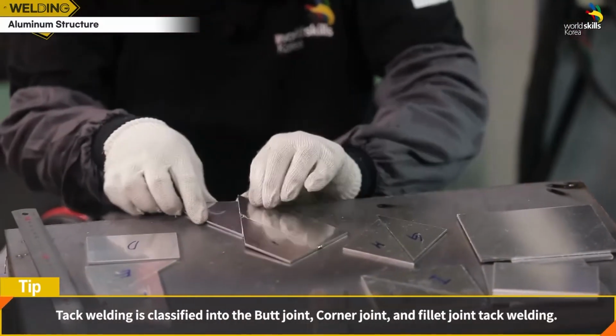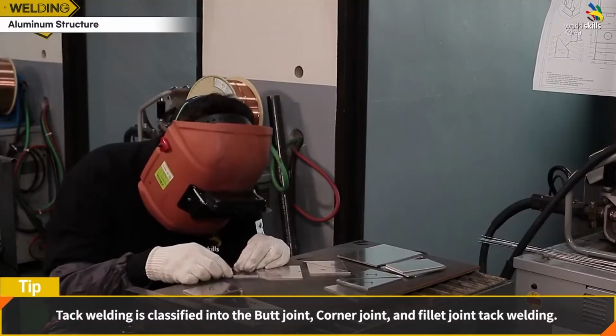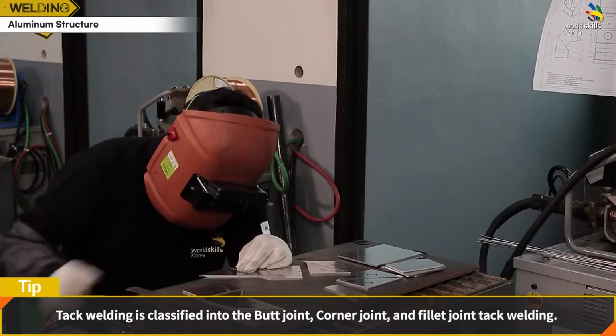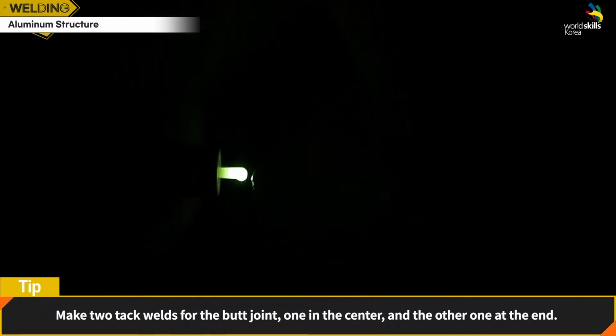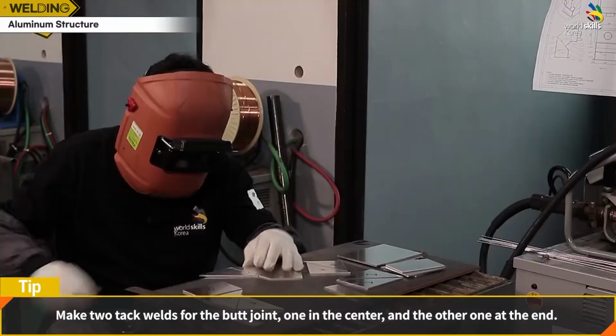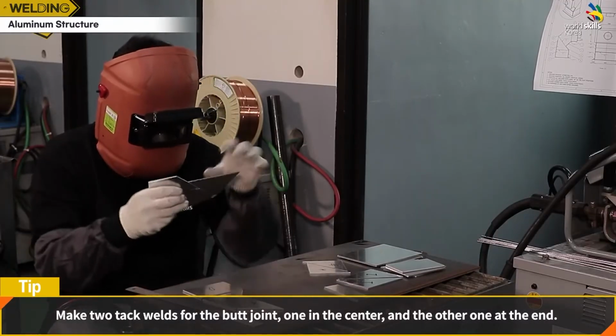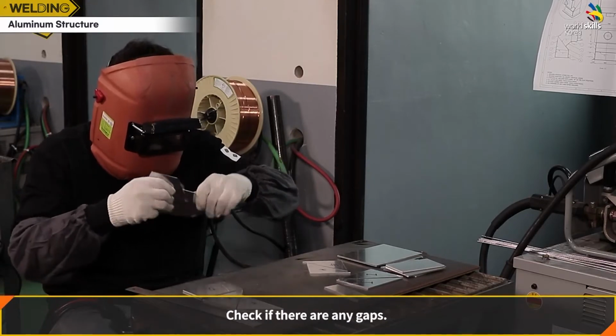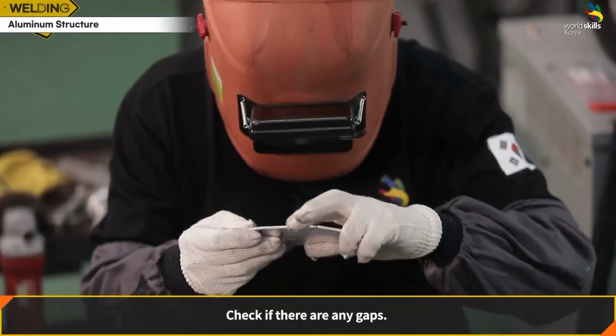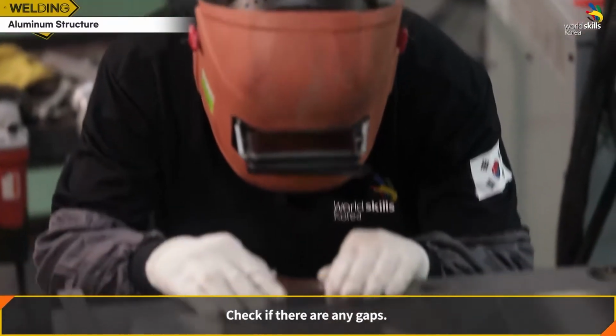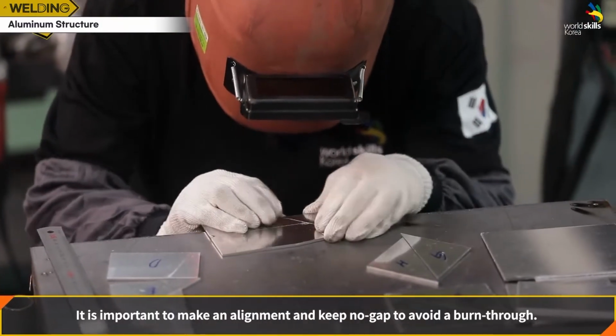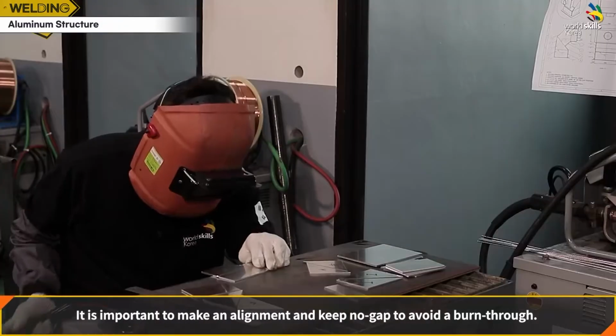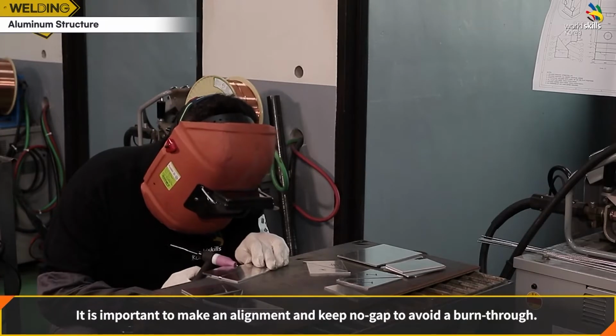Tack welding is classified into butt joint, corner joint, and fillet joint tack welding. Make 2 tack welds for the butt joint, one in the center and the other at the end. Check if there are any gaps. It is important to make an alignment and keep no gap to avoid a burn-through.